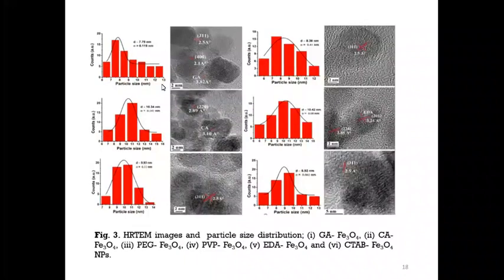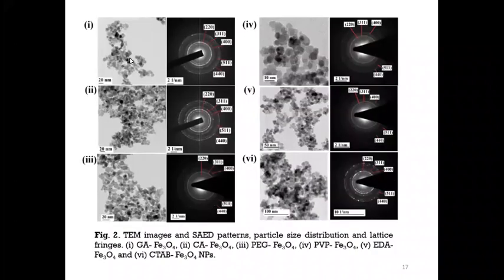I have given a precise size, so you will see the size with glutamic acid. So this is glutamic acid, it's 8 nanometers. This is citric acid, 10 nanometers. Then it is 9.93. This is the average size with, of course, a standard deviation. So all the nanoparticles are around 10 nanometers. During the co-precipitation technique, of course, there is certain variation, plus minus 2-3 nanometers. However, all are almost monodisperse, and the nanoparticle formation is confirmed.